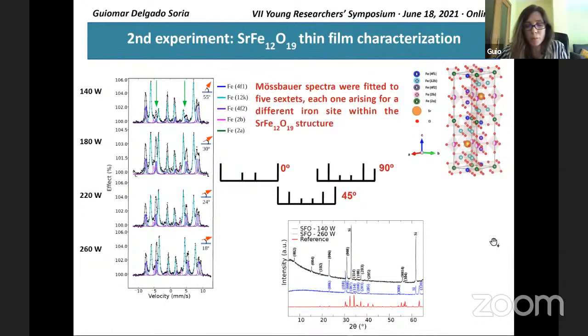First, we grow the thin film strontium ferrite by magnetron sputtering, and we determine its structure and magnetization by different spectroscopy and diffraction techniques. We emphasize in our work Mossbauer spectroscopy, which provides information of the iron sites in the crystallographic structure, as well as the magnetization in the thin film. We determined that the sample with the layer grown at the highest power deposition, as well as the highest thickness, has the magnetization within the plane.